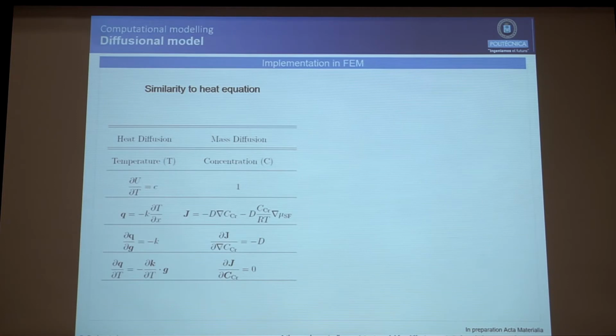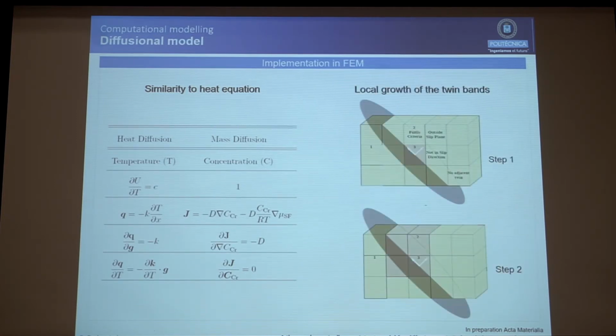It's a non-local problem because as the twin is growing, you need to take that into account when you are rotating the element. So we are also taking into account a kind of non-local model, because for every element we check if the surrounding one has twin or not. So the twin can only propagate into the direction of a slip.